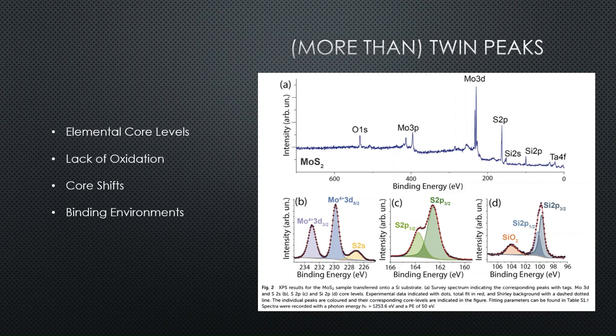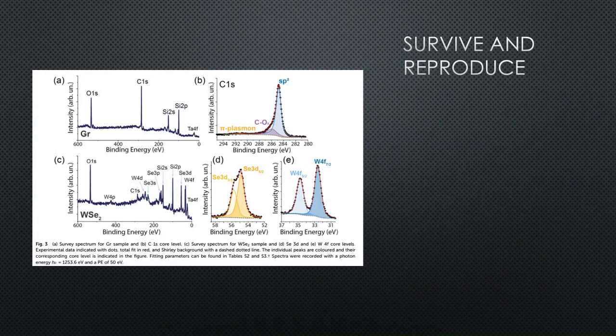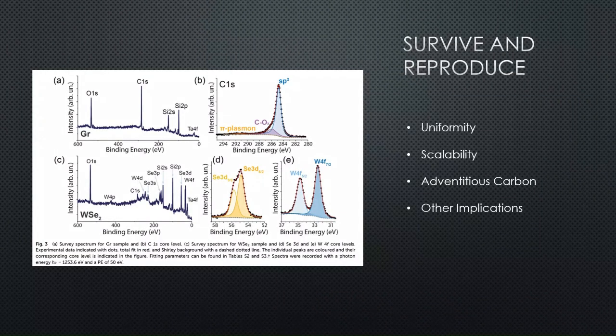The study also used the XPS to probe the chemical state of the atoms. For instance, the absence of extra peaks or shoulders in the metal or chalcogen spectra provided evidence that the bonding environment was not disturbed by the exfoliation process. One significant finding was that the high throughput exfoliation method yielded consistently high quality surface results across multiple samples. The XPS measurements taken at different spots on the same flake or across several flakes showed very similar spectral profiles, and this reproducibility is critical for the practical application of industrial scaling.